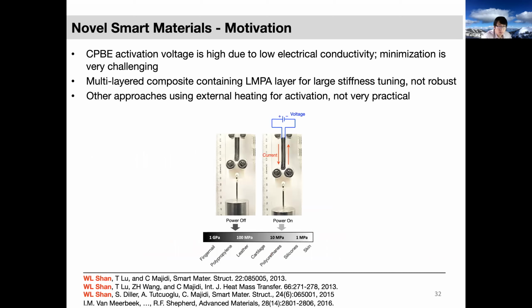So when we talk about this CPBE, or LMPA for the soft gripper, we have been using this for the ligaments and the core. I mentioned that the CPBE activation voltage is high because its electrical conductivity is low, since it has copolymer elastomer mixed with carbon black. Carbon black is not that conductive. And because of the size of the additions, the miniaturization of this structure is also very challenging, because the carbon black particle can easily go to roughly 50 micron. That size limits how thin you can go using CPBE.